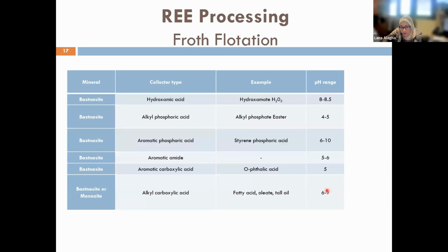Here are some of the collectors. Again, the collectors are added to render the surface of the mineral hydrophobic and enhance the attachment of the mineral particle with the air bubble, and of course, improve the flotation efficiency. And in some cases, you have to think about kinetics also. When you design your flotation operation, you have to think about kinetics as well. A shorter time means that you are going to have maybe higher recovery but poor grade. More retention time is actually going to negatively impact your concentrate grade.